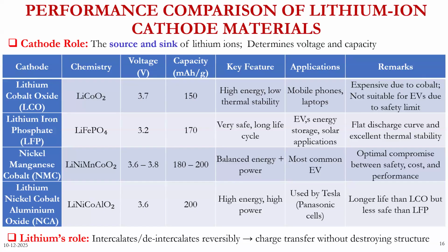The last one, which is again coming into the picture nowadays, is around 200 mAh per gram capacity. This has a very high energy and high power. This is what is used by Tesla in their electric vehicles. There is an advantage, it has a much longer life compared to all, but the problem is with respect to safety. Out of all, lithium iron phosphate is safer. Because of its high thermal capability, LFP is considered to be safer. Along with that, it also has a flat discharge curve.